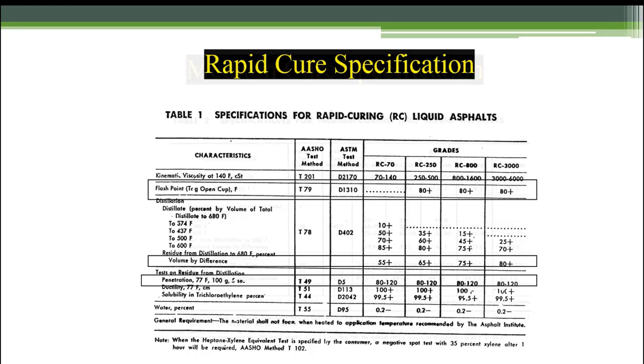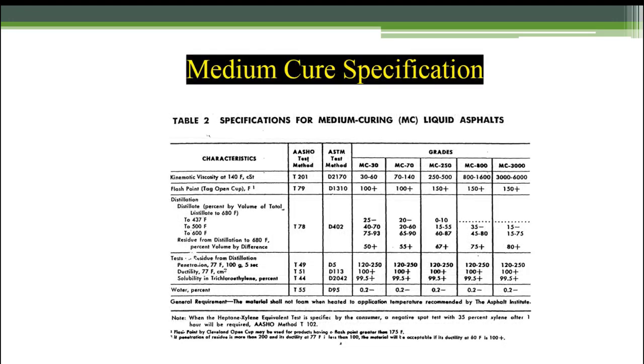If we go to MCs, you can see this by the same line. Obviously, our cutback, our solvent now, is diesel or kerosene or a combination of the two. So for our flash point, again, lower viscosity is on the left side, higher viscosity on the right side. Lower viscosity means it flows easy. Higher viscosity means it flows harder, or is more difficult to flow. On an MC70, for example, the flash point is 100 plus, a minimum of 100 degrees Fahrenheit.